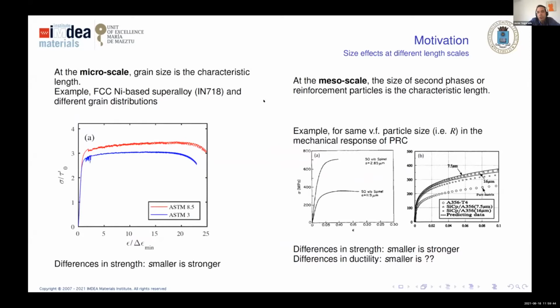When does it happen? At the micro scale, this is something very common that we find, that we call the Hall-Petch effect. We have the same grain size distribution, the same heat treatment, the same material. Here, an example is IN718, and just the variation of the average grain size produces different behaviors. In this case, the smaller the grain, the stronger the response. At a larger length scale, when we have, let's say, particles or inclusions embedded in a metal, for the same volume fraction of particles, we can have an effect on the actual size of the particle.